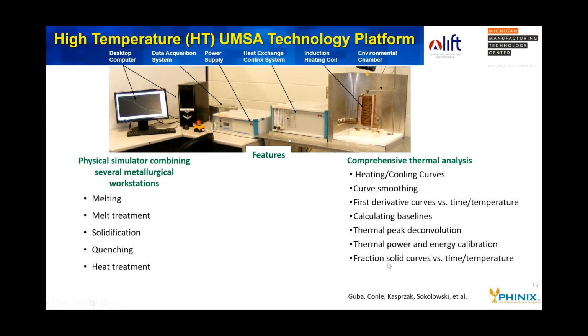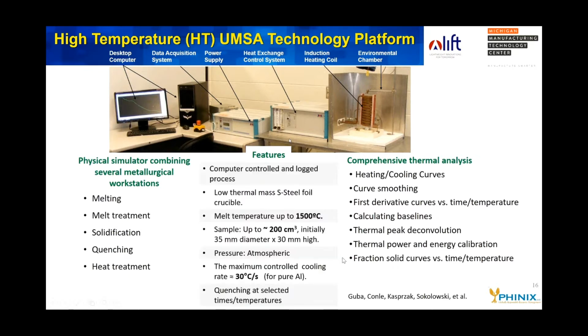So the physical simulation can do melting, melt treatment, solidification, quenching, and heat treatment. And the analysis has a comprehensive thermal analysis that is done on that. This particular apparatus can heat the metal to 1500 degrees. It can use samples of up to 200 milliliters, and can cool those samples at the rate of up to 30 degrees a second.